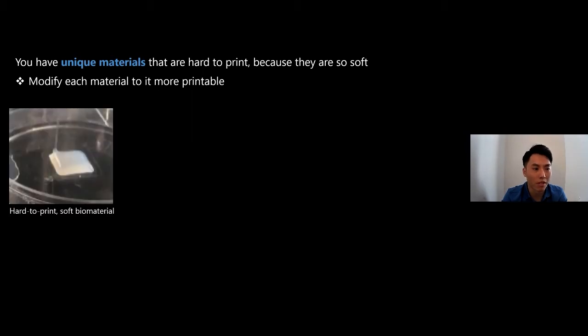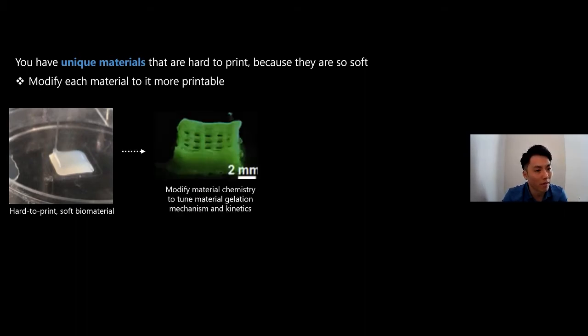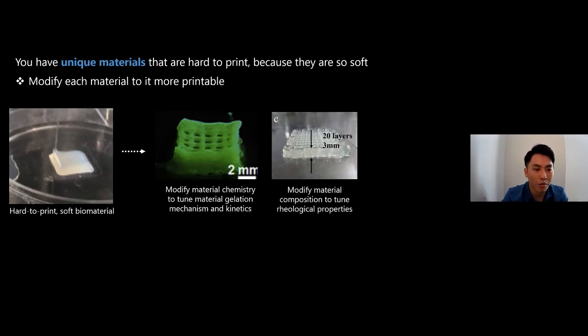So, for example, you can imagine this print that we previously showed. It's a very difficult to print soft biomaterial. What a lot of people have done is to modify the material chemistry itself to tune the material gelation mechanism and kinetics, right? So for example, incorporating UV cross-linkable material so that upon extrusion onto a platform, you're rapidly cross-linking by UV light. Another approach is to modify the material composition to then tune its rheological properties. So adding in rheological modifiers so that it's capable of standing up in air and capable of being stacked layer by layer on top of each other.